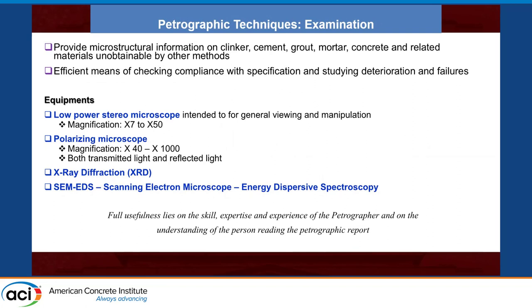It is important to note that SEM is a combined approach — SEM doesn't give all the answers alone. We need to apply optical microscopy first: observe a 3-inch by 2-inch thin section to get all the features, identify where you need more specific information, and then use SEM for detailed observation. Optical microscope and SEM together give you a complete picture.